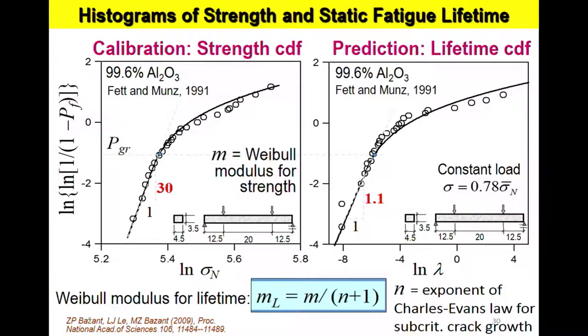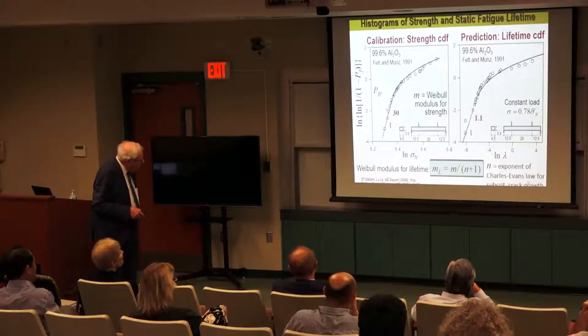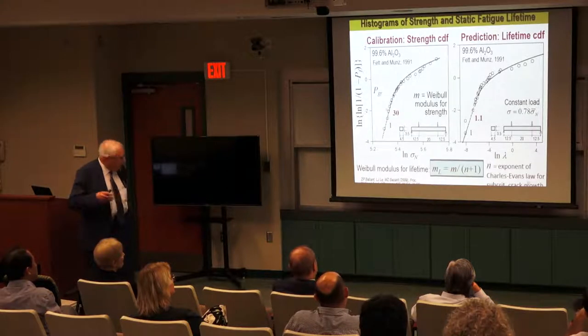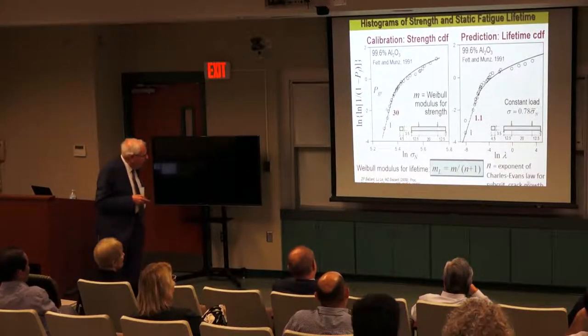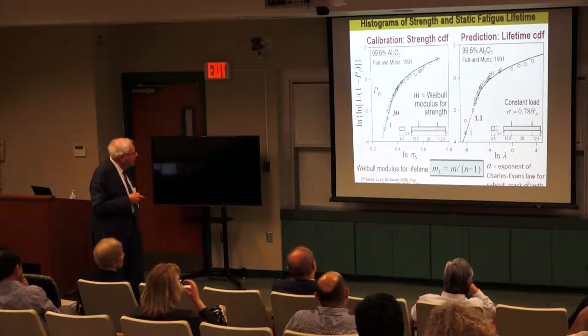In fact, it can be shown, analytically derived, that the Weibull modulus for lifetime is the Weibull modulus for strength divided by n plus 1. Here n is the exponent of the subcritical growth law, so Charles Evans' law, or in cycling it would be Paris' law, which is on the order of 4 to 12, something like that. And this is one case where we can verify it.